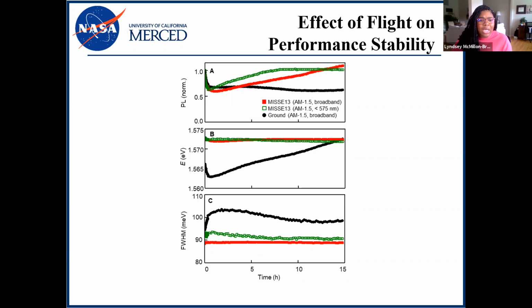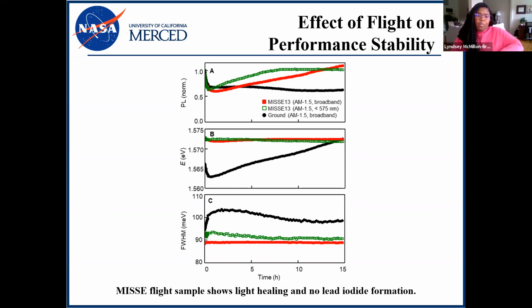And in panel C, we're taking a look at the full width half max, and that's a measure of the amount of defects in the sample. If we see a narrow full width half max, we would say our material has fewer defects, so the film's emission is closer to its pure band gap. Our ground sample is a bit bizarre here actually, but the flight sample is the more ideal performer. So overall, from this analysis, we conclude that the MISSE sample is more stable and it exhibits light healing, and we see no lead iodide formation.